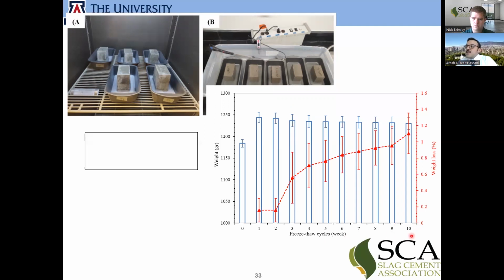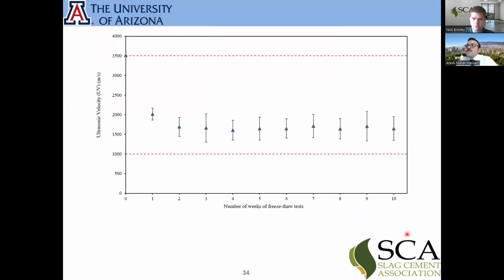At 10 cycles, you see that each week we are seeing a decrease in the weight of the samples. But what is the weight loss ratio? It's only 1.1% weight loss after 10 cycles of freeze and thaw. And we did ultrasonic testing on the samples to make sure there are no cracks developing inside them, because just measuring the weight is a good indicator, but not good enough to say that the materials are durable. We need to do a more detailed study.